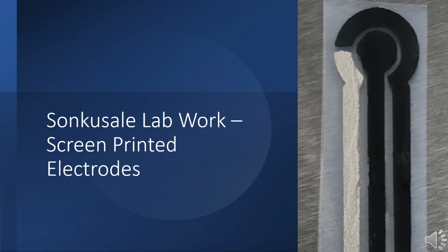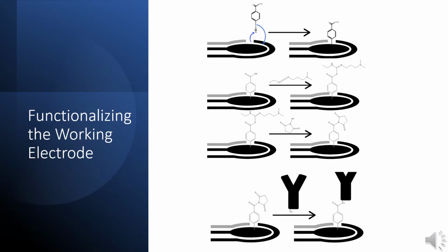I have made this electrode design in GIMP photo editing software and screen-printed conductive carbon paste for the working and counter electrodes, and a silver chloride paste for the reference electrode. This design fabrication requires functionalizing the working electrode through diazotization and EDC-NHS coupling, which can be seen to the right. For a proof of concept experiment, cortisol antibodies were immobilized onto the working electrode surface.